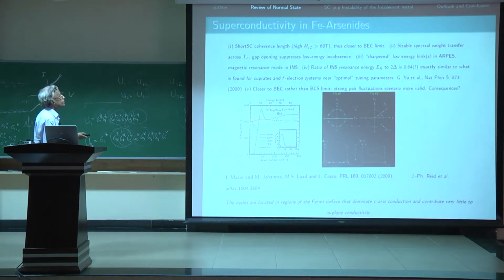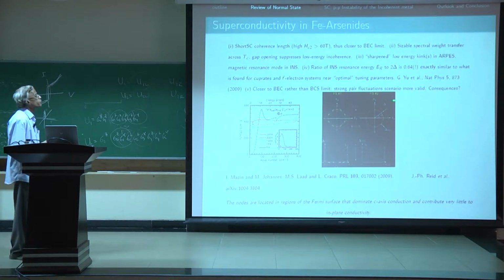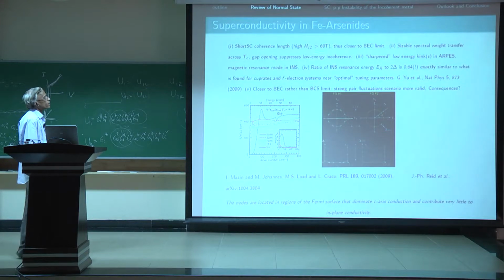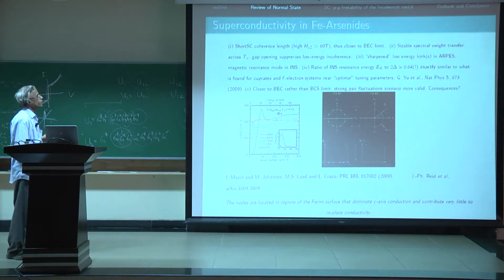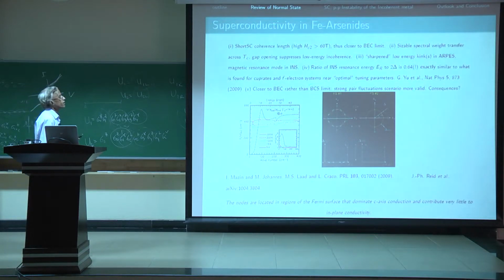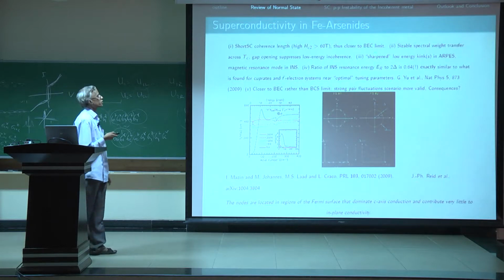Okay, so this is more of the same. Other similarities with the cuprates. So there is sizable spectral weight transfer across the superconducting transition. And as expected, this is a coherence restoring transition because the normal state is heavily incoherent with no well-defined Landau quasi-particles, but a gap opening gives rise to coherent features below Tc, exactly as what is seen in cuprates.